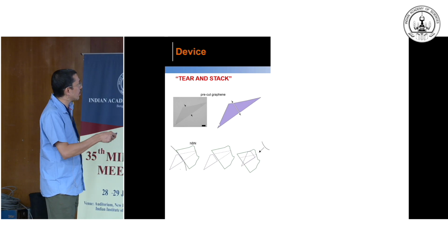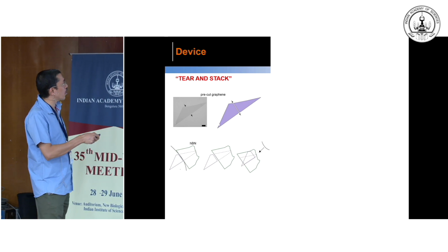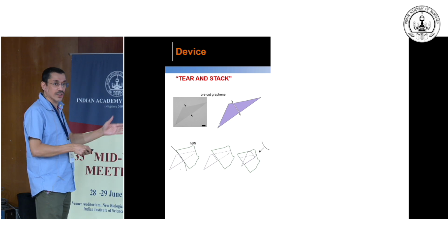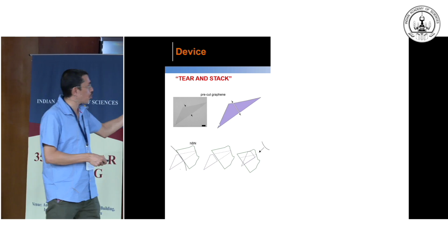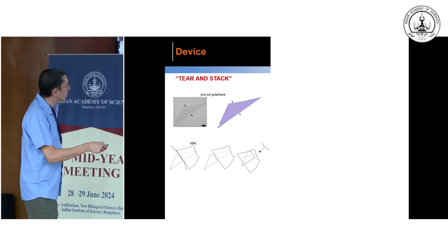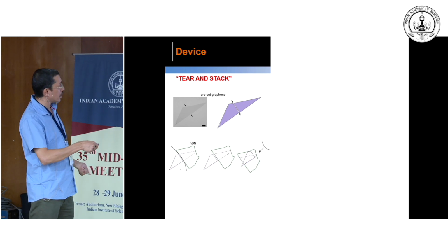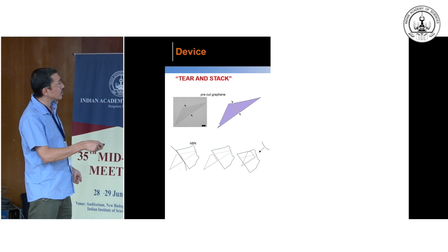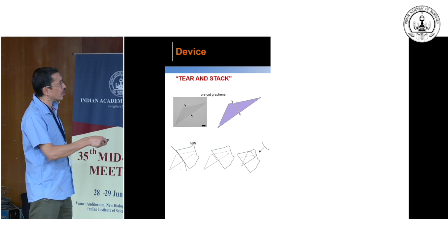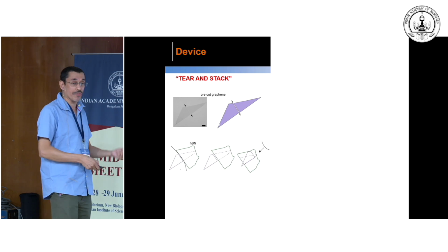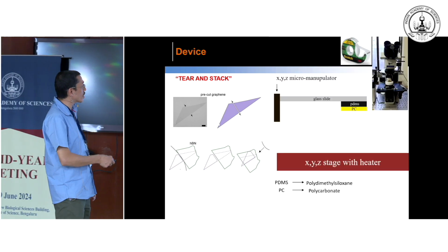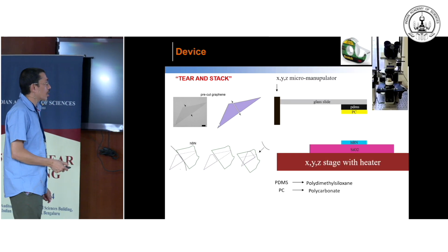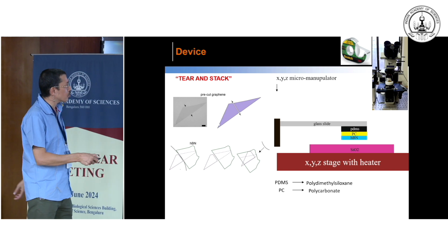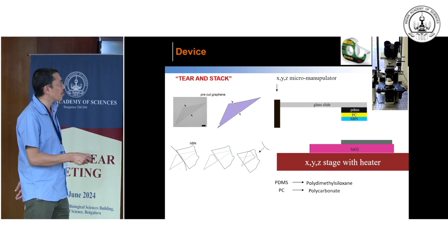The way we make a device is a well-known technique called the tear and stack technique. Pablo will show us how to do that. We take a single graphene sheet and cut it into 2 pieces, and we make a relative angle between them, because you have to maintain the same crystallographic axis from the single piece. So that's the way we make a twisted bilayer graphene. This is a cartoon schematic of how you make it.